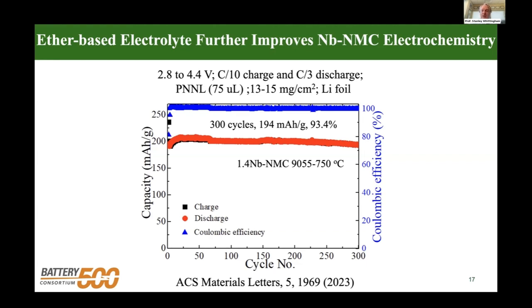So I'd advise all of you watching here, when you read a paper in literature, you see what loadings they're using in milligrams per square centimeter. A lot of people will be using very low loadings, 1 to 2, which are meaningless, also using a large amount of electrolyte. We use here the minimum amount of electrolyte we can get these cells to cycle with, which is what you need in a practical device.